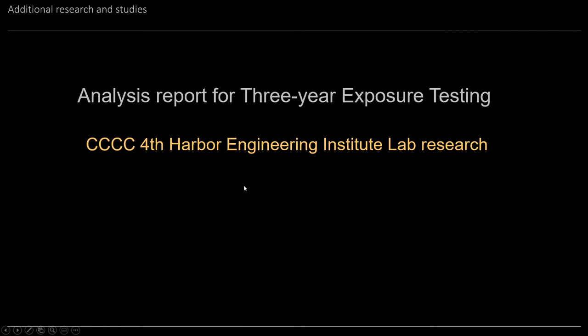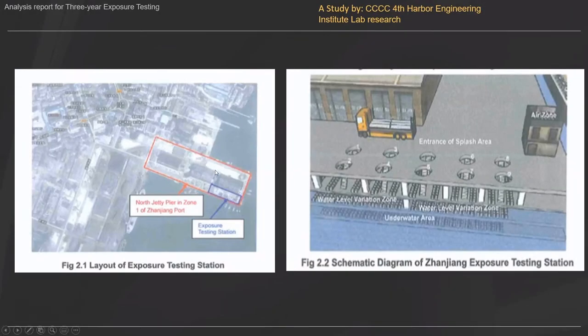Some work that was done by the CCCC 4th Harbor Engineering Institute. This is looking at exposure testing, chloride-induced corrosion potential. This is the test site adjacent to the sea in a jetty, and there are various zones: underwater, at splash level, and in the air zone. There are samples of concrete placed in all of these just to look at the performance of different types of concrete.